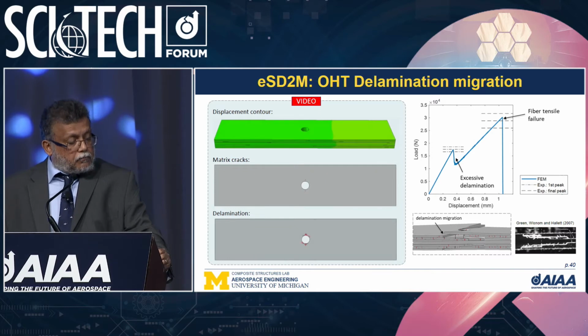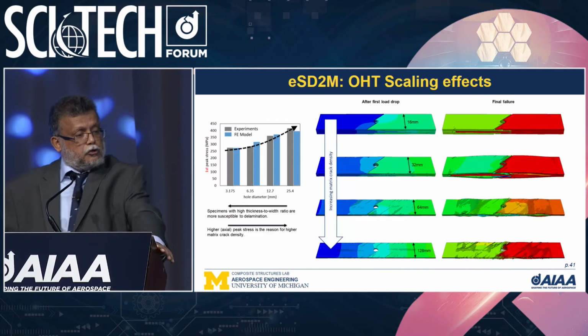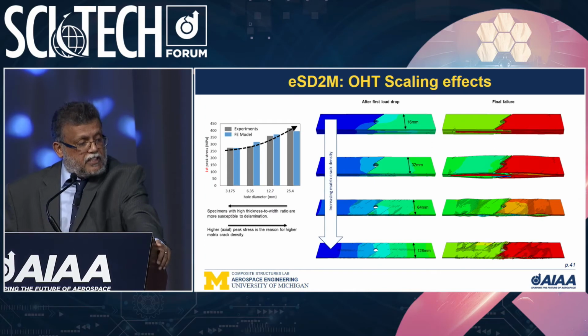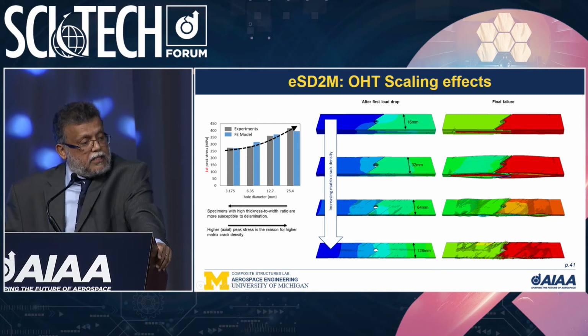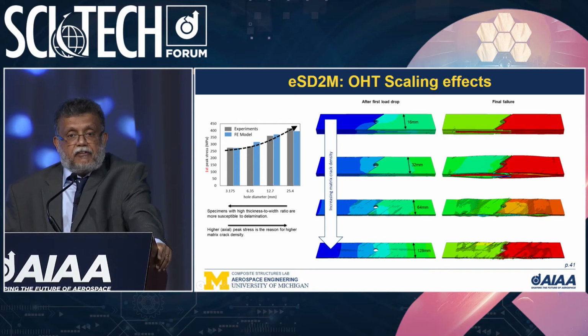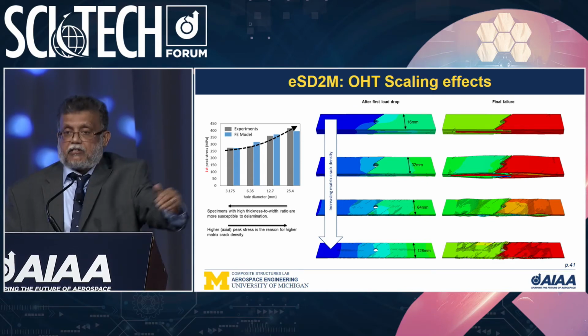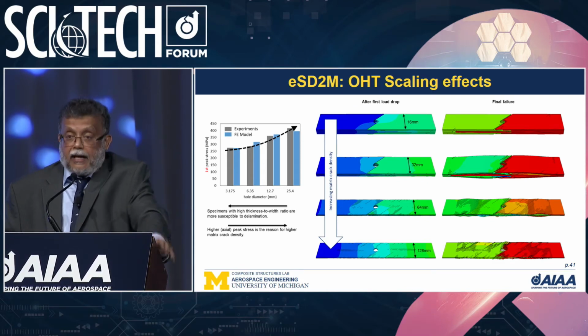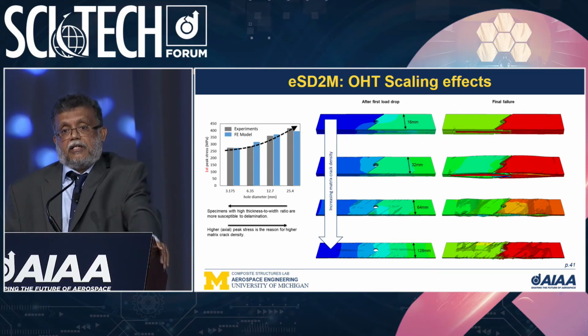Next I want to show this same for the different scaling that we did, and you can see the experiments and the FE model are very much in tandem, showing the final failure of these types of laminates captured very accurately with the interaction between matrix cracking and delamination, and the migration of the delamination as well.